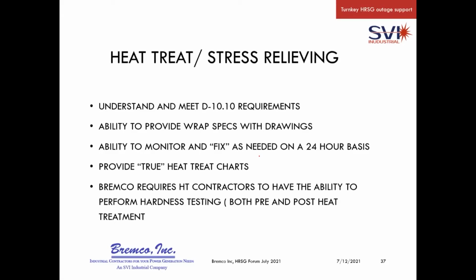The requirements obviously are to understand and meet D1010 requirements for wrapping. They should have the ability to provide you wrap specs with the drawings, and the ability to monitor and fix as needed when they lose a thermocouple or something changes from their weld. They should be able to monitor that on a 24-hour basis and have the ability to make the changes. One of the things I was taught by a stress relieving company is when you receive your heat treat charts, some of the companies give you just one clear line to show you their heat treat analysis, or their ramp up cycles and everything else. And you'll see everything falls along the line. Question that immediately, because you have different thermocouples on there. So you should have multiple lines that identify the readings that the different thermocouples are getting.